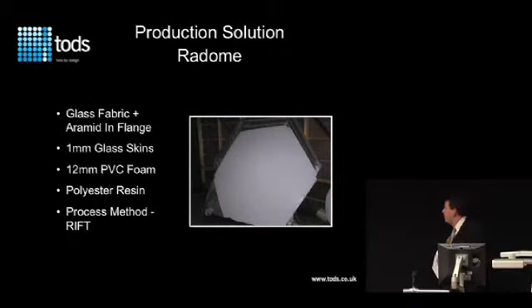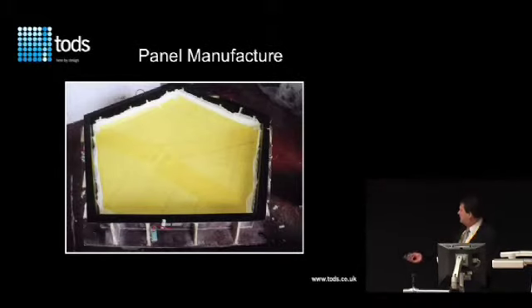Now this particular one is glass fabric, aramid in the flange to improve the bolting area, 1mm glass skins, PVC foam, polyester resin, and the process we decided on was RIFT, or Resin Infusion. The main reasons being that it's a simple shape, you don't have any problems holding the material where you want it to hold, the properties which you get are very good and reproducible, and it's a low-cost method. The materials. That's a typical panel in manufacture.